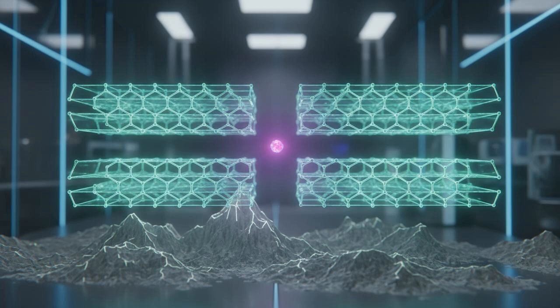The team used anvils made of molybdenum disulfide, or MoS2, monolayers. MoS2 is atomically flat, chemically inert, and has no dangling bonds. The process involves placing a small bead of low melting point metal, like bismuth or tin, between two of these MoS2 anvils. They heat the stack until the metal melts and then apply immense pressure, specifically around 200 megapascals. To give you a sense of scale, that is roughly the pressure you would feel at the bottom of the deepest ocean trenches.